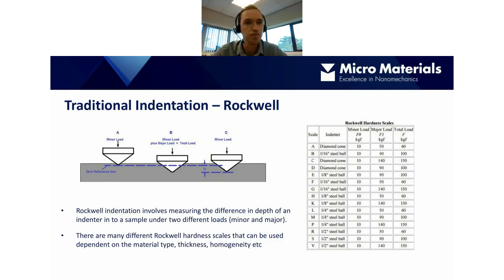And similarly with Rockwell indentation, slightly different here. This starts off by applying a minor load. As you can see on this table on the right, we have various different scales for the Rockwell hardness test, and it tells you the minor load, which is 10 kilogram force, and the major load, which is variable depending on the scale. What we're measuring here is the difference in depth of the indenter between these two loads, minor and major. The different scales are for different types of material. It also depends on the thickness and the homogeneity of the material. Not only does the major load change, the indenter also changes depending on the scale. You can see there are some diamond cones here, and the rest of them are steel balls from 1/16th to half an inch in diameter.